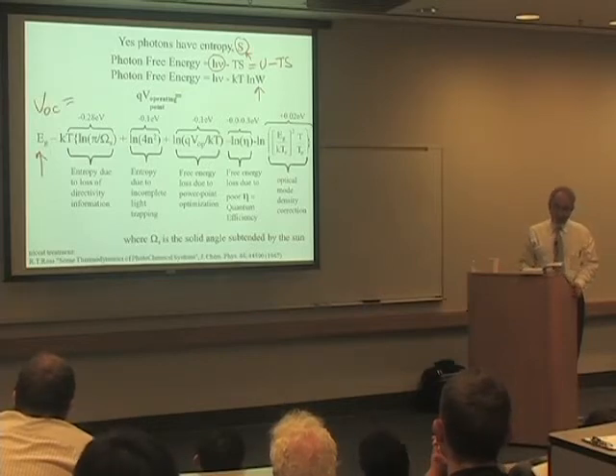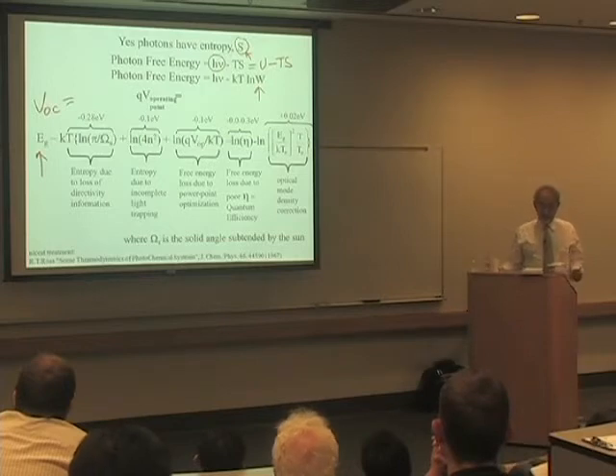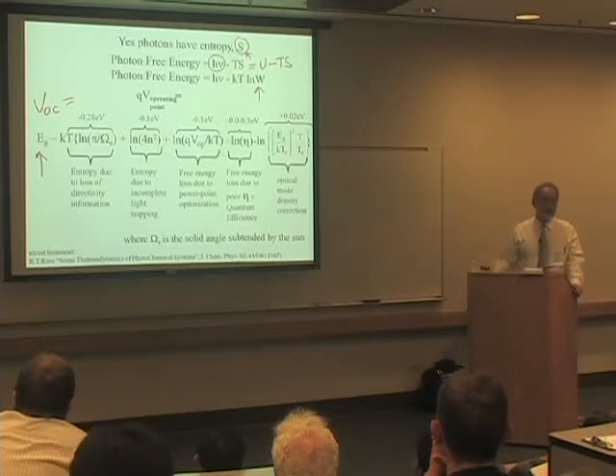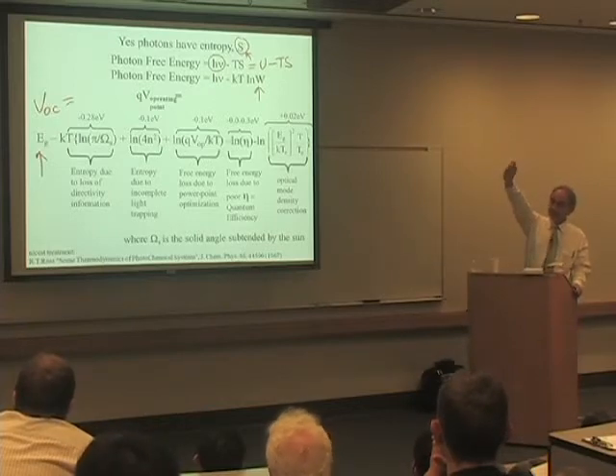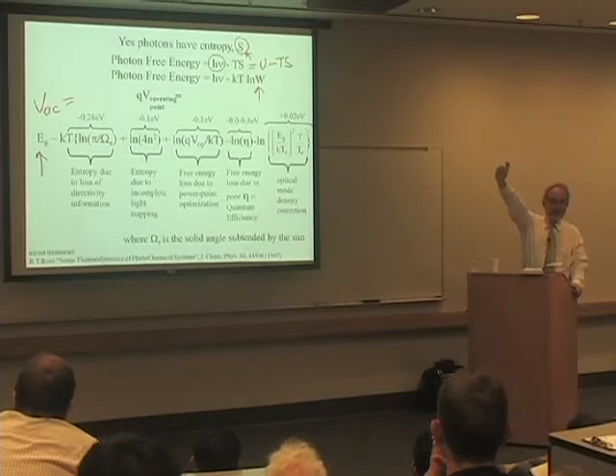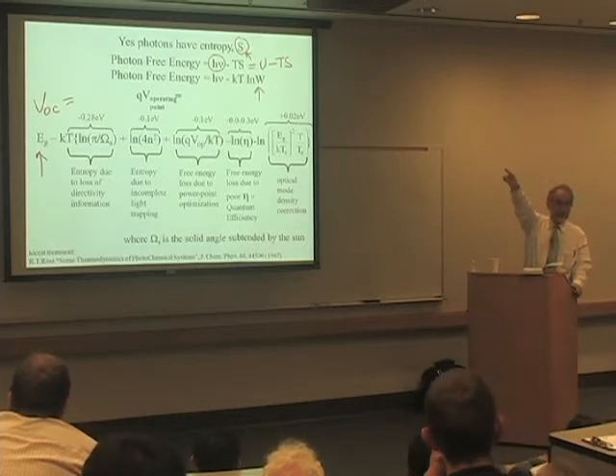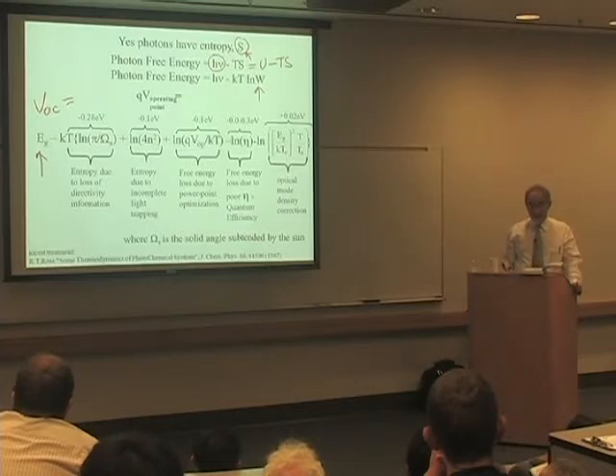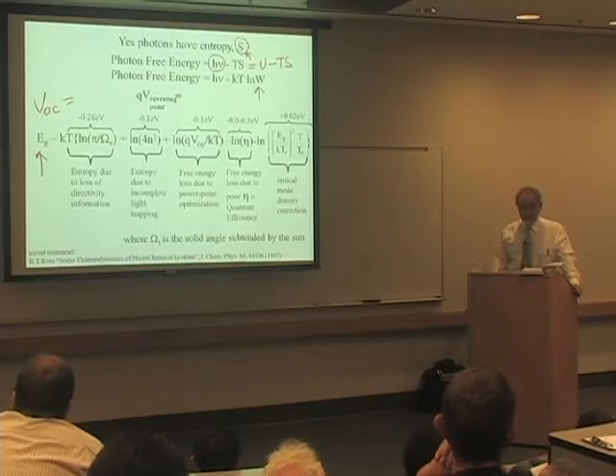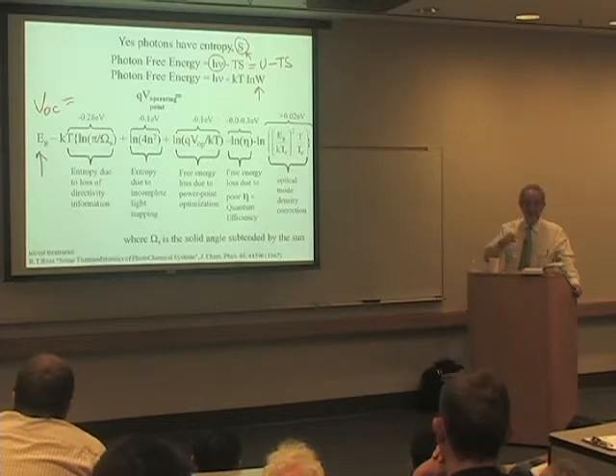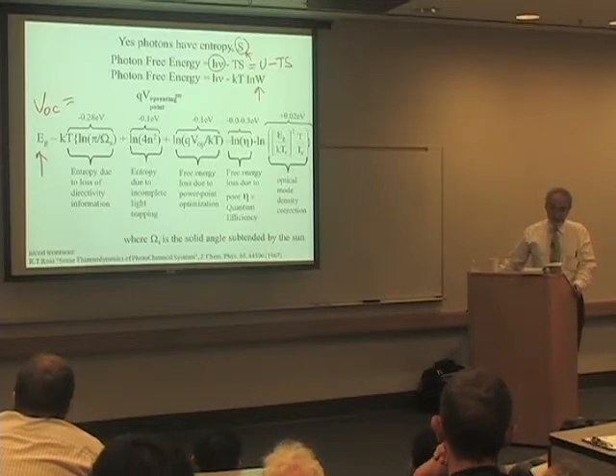You start at the band gap. And then you start giving up entropy terms. Now, so what is your dominant entropy term? And it has a very simple physical explanation. Let's say the sun is up in the sky, and it subtends an angle of about half a degree in the sky. So you know the rays are mostly coming from the sun, okay? But at the end of the day, when we make the solar cell, you've completely thrown away all the information of the direction that the sun was in, because you need the solar cell to accept other directions as well. So you had information, and you threw this information away, because the solar cell does not use the directivity information, it accepts rays from all directions.